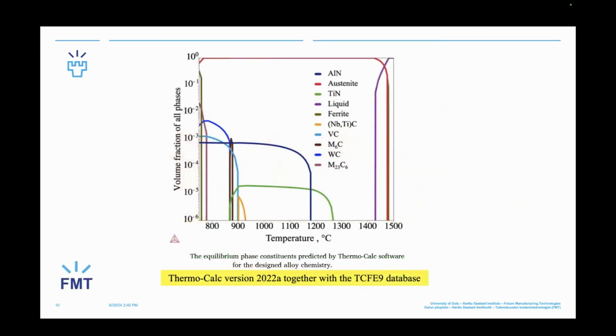Okay, this is a Thermo-Calc calculation for the first steel using the TCFE database. You can see different carbides that enhance the strength and yield strength, mainly tungsten carbide, vanadium carbide, and niobium-titanium carbide, and mainly austenite here. So during air cooling it will be mainly martensite.